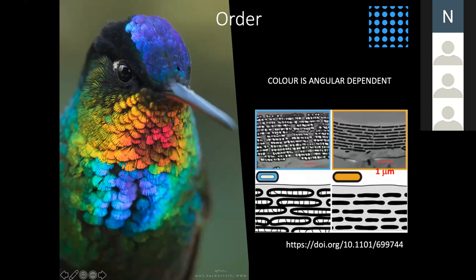So when I say ordered structure, a good example is this really nice color of this bird. As you can see here, in these feathers you can see all the different colors from the rainbow, from red to orange to yellow to green, and also almost ultraviolet. And as I was telling you before, this structural color, which is really angular dependent, comes from a layered structure of melanin that is inside the feathers, the barbules of this bird's feathers.